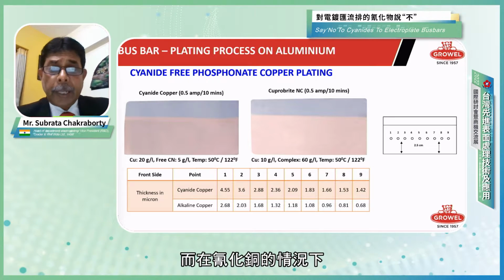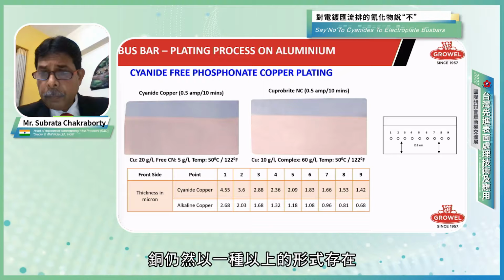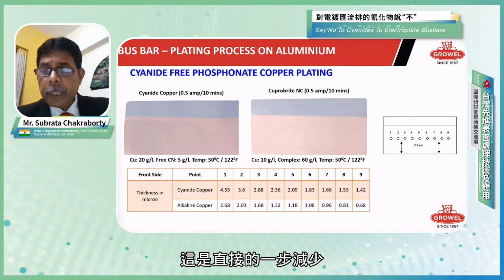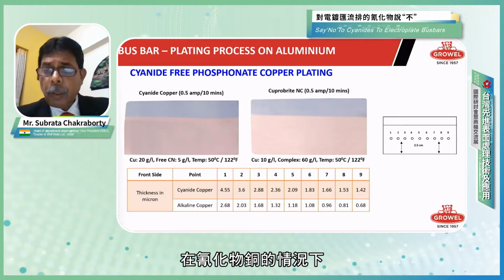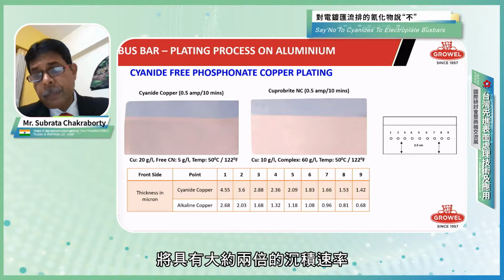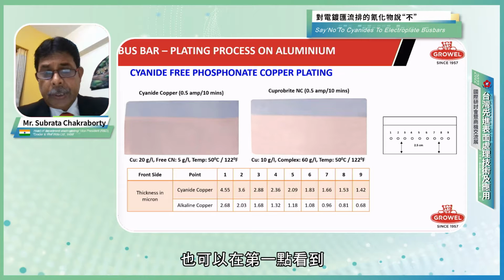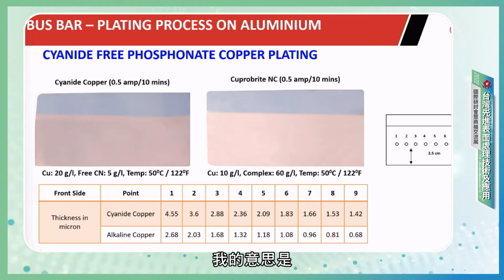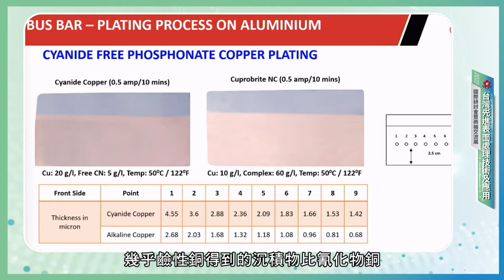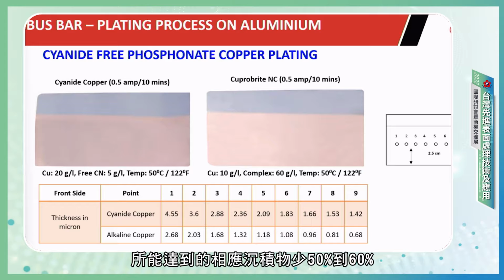Whereas in case of cyanide, copper remains in +1 form, so it is a direct one-step reduction. So each coulomb of electricity passed will have approximately twice the rate of deposition compared to alkaline copper. This can be seen in point number 1 here, and these are the different points. This is the high current density zone, and this point number 9 is the low current density zone. So at each and every point, you can see that with alkaline copper, we are getting virtually 50 to 60% less deposit than the corresponding deposit achieved with cyanide copper.